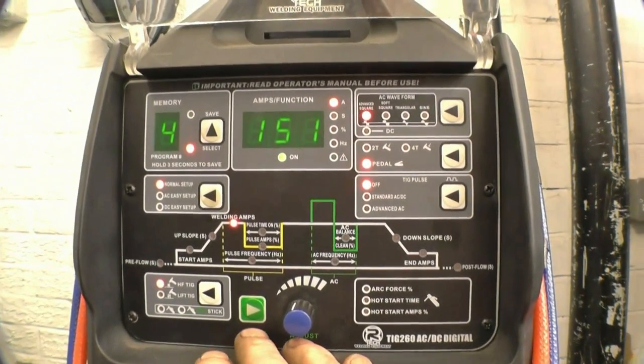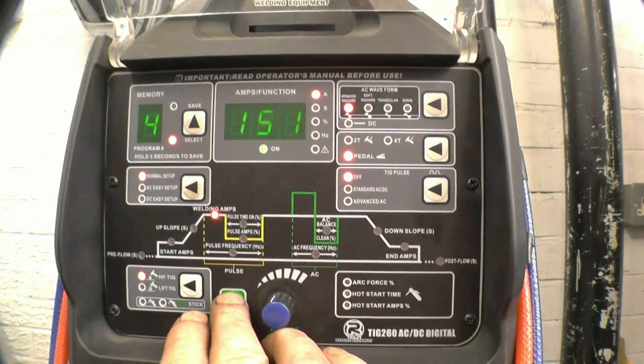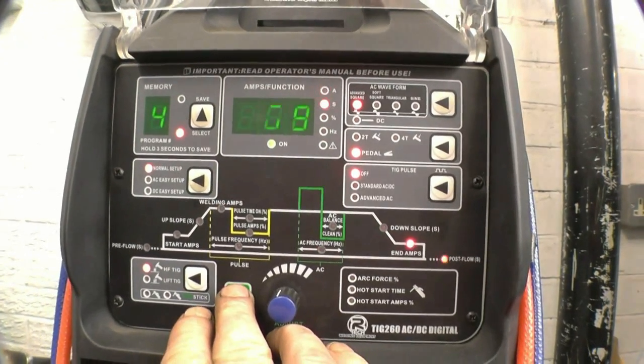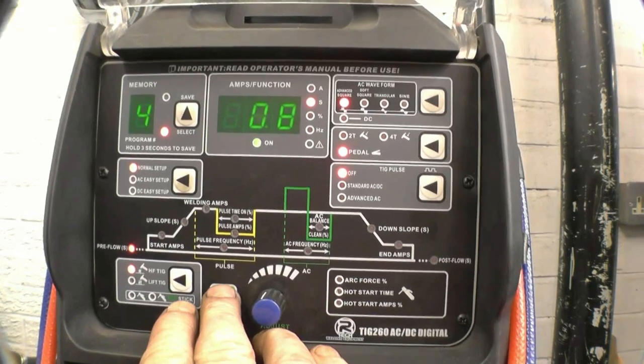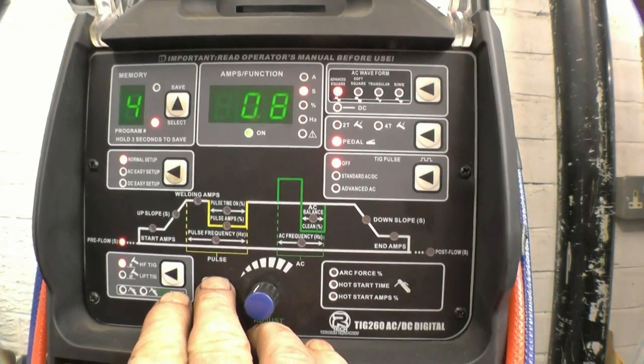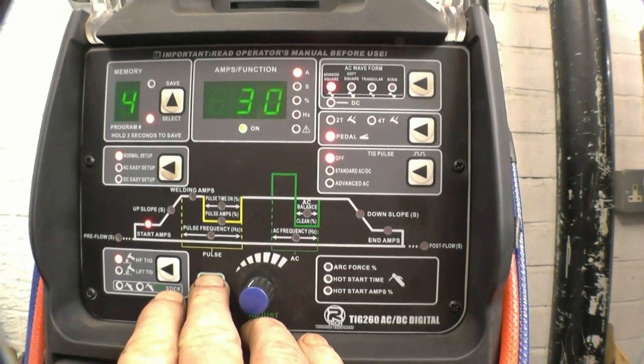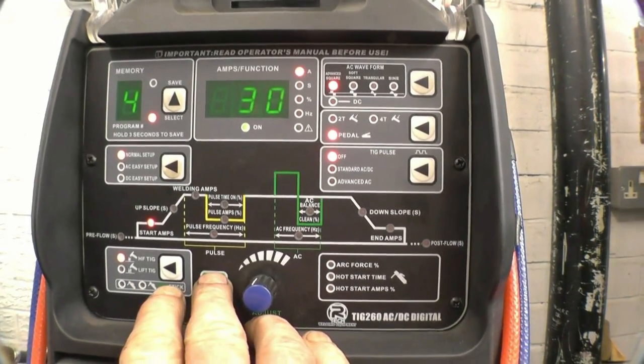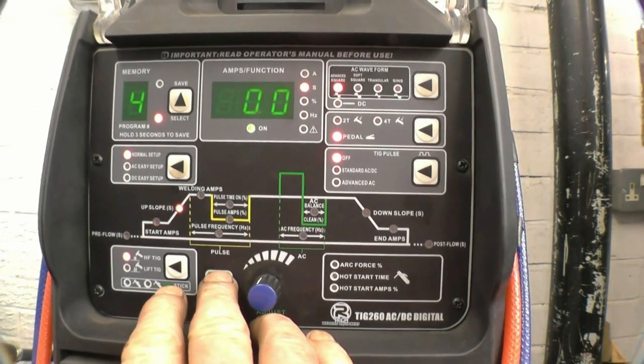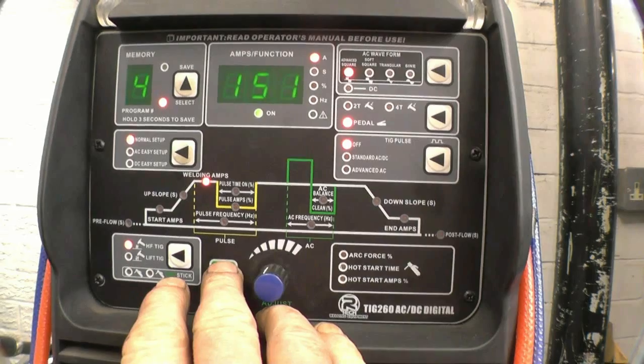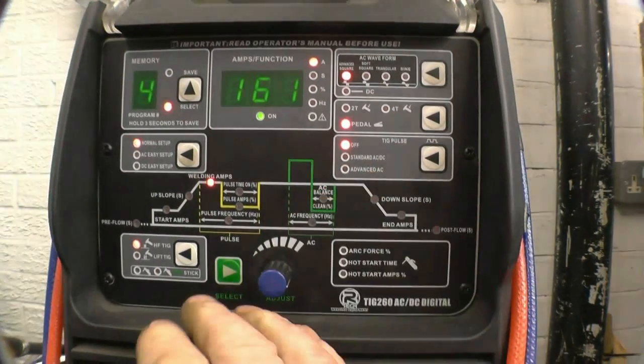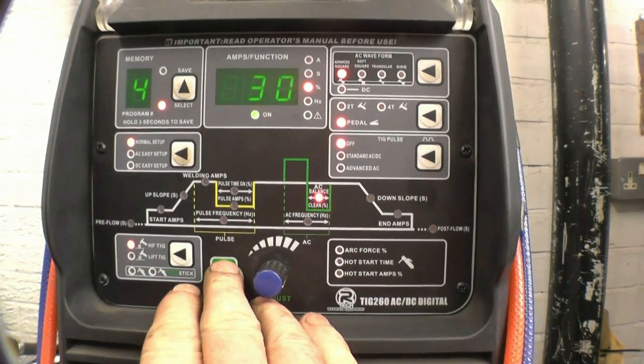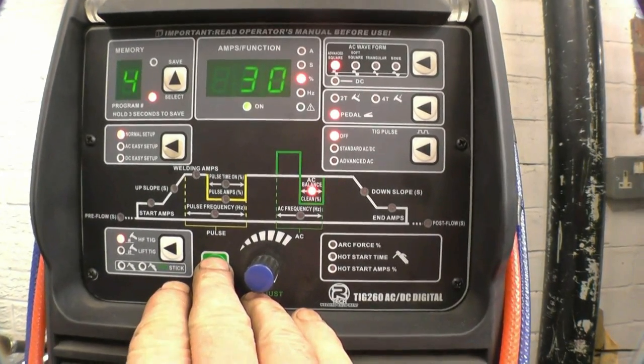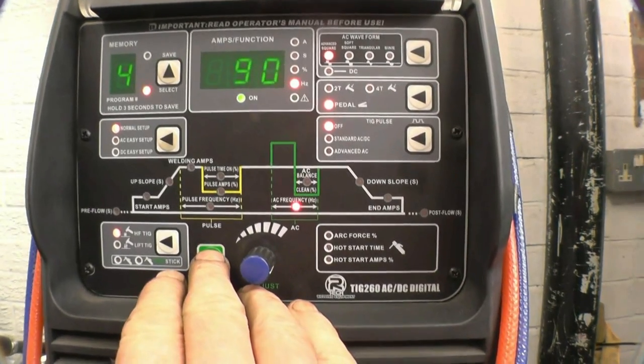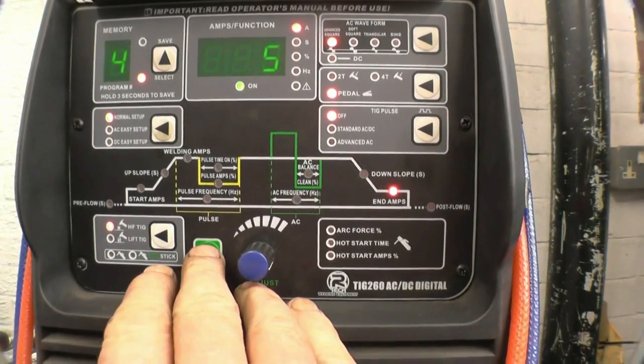Right, these are the settings I'm going to weld it on. Obviously AC, start at the beginning. Pre-flow gas, there's no pre-flow because I'm using a pedal. Start amps 30 amps, so I get a nice clean start. No upslope because I'm using a pedal. Welding amps 160, more than enough. AC balance 30% clean. AC frequency 90 Hz. Downslope, no downslope. End amps 5, as low as it'll go.